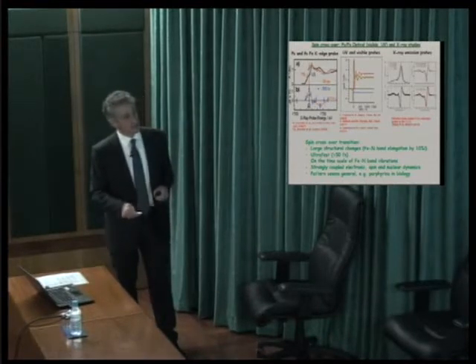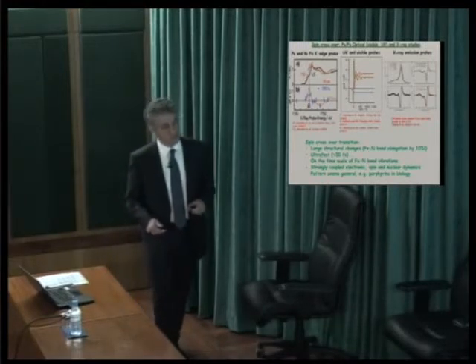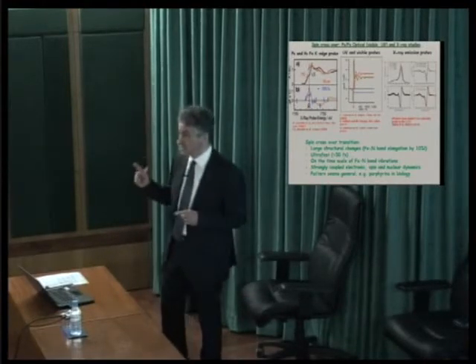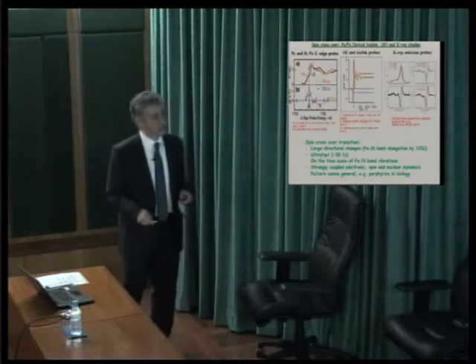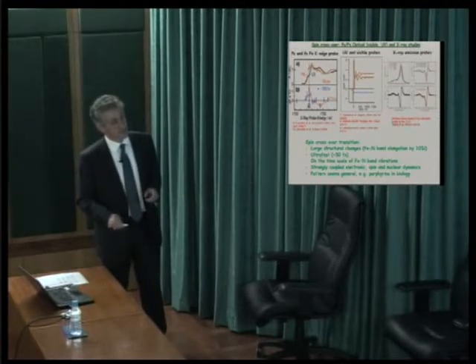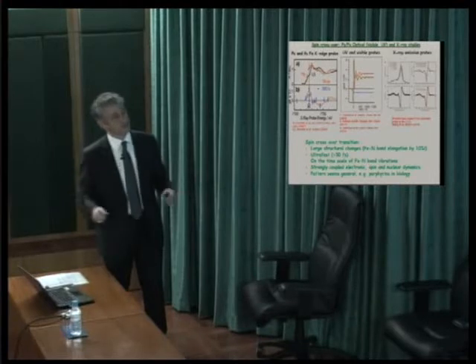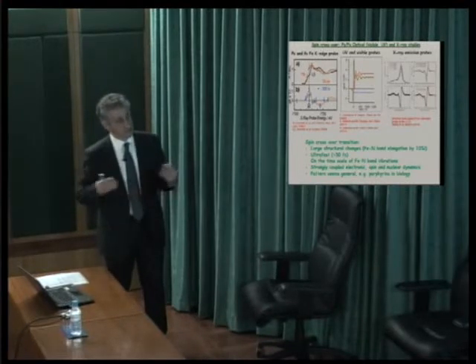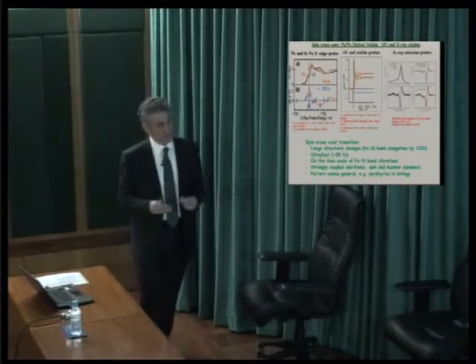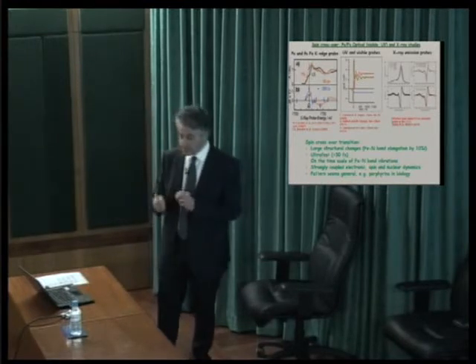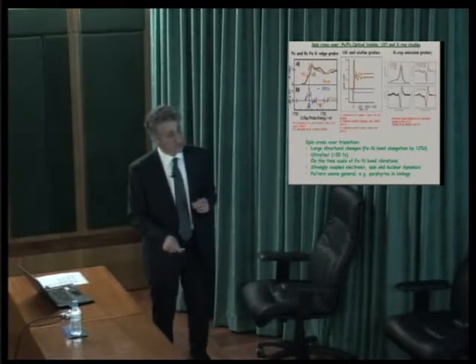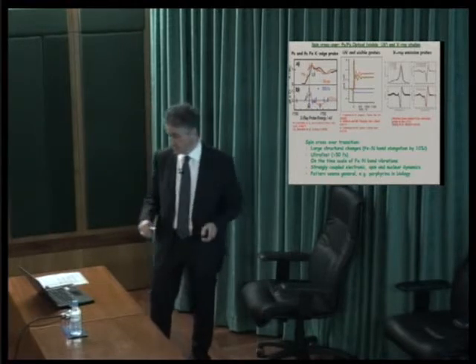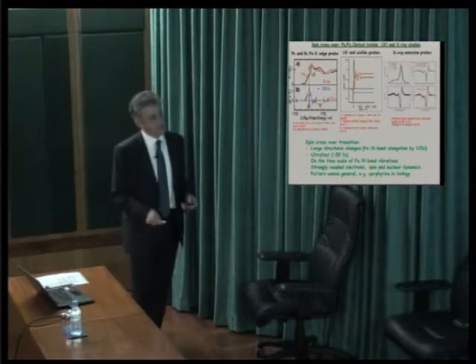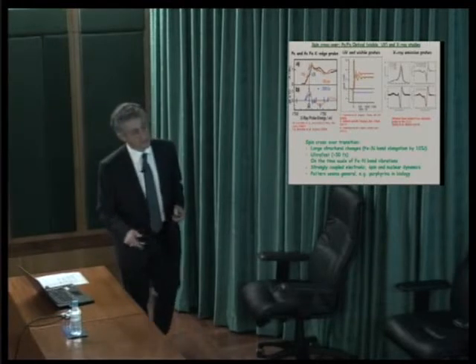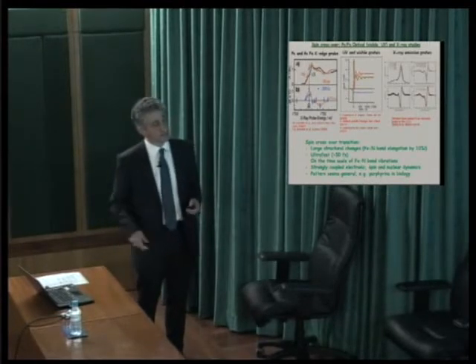And one of the very remarkable findings was that the spin change takes place in less than 50 femtoseconds, delta S equals 2. This is very unusual. And it takes place on the time scale of the Fe nitrogen bond vibrations, which tells you that basically nuclear spin and structural dynamics are very strongly coupled and they are concurrently taking place. And this is a fairly general pattern, and porphyrins in biology are doing exactly the same thing.